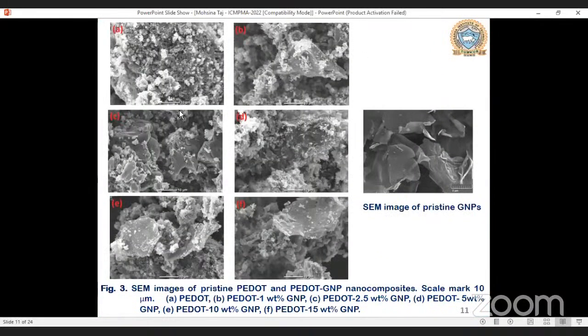Some images of the pure PEDOT and composites were taken. Image A shows the SEM image of pure PEDOT. Irregular shaped particles were observed, and in the SEM image of graphene nanoplatelets, we have observed platelet-like structures. When we increased the concentration of graphene to 15%, we observed that these platelet-like structures are covered with the irregular shaped particles. This results in an increase in distance between the platelets. This may cause a reduction in the van der Waals force between the platelets and hence a reduction in the agglomeration and better dispersion of platelets in the composite.